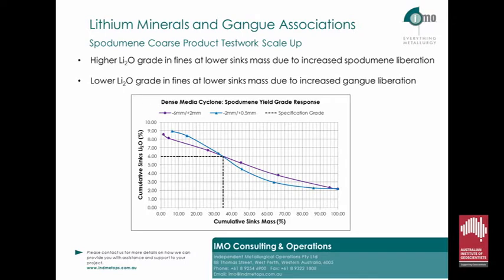This slide shows dense media cyclone modelling conducted by IMO on two size fractions, a coarse and fine size fraction. The model targets a lithium oxide or lithia grade of 6% at a low cumulative sinks mass, which is at the left-hand side of the graph. The fines product, which is the top line, is higher, whilst at the lower sinks mass, the coarse product is lower. The higher lithia grade of the fines compared to the coarse at the reduced sinks mass is due to the increased liberation of the spodumene at the finer size, resulting in a more efficient separation and lower gangue mineral recoveries.